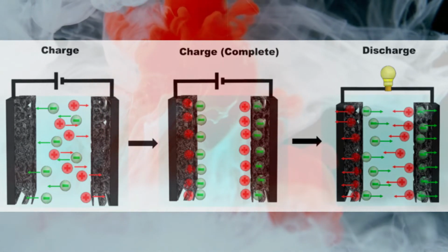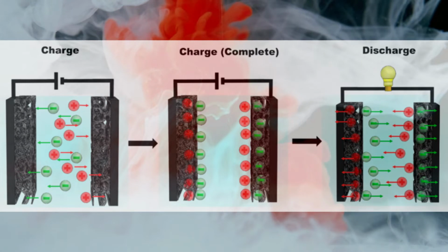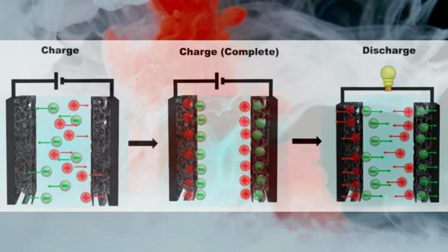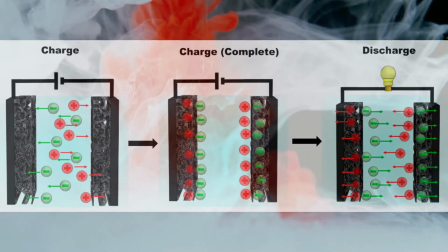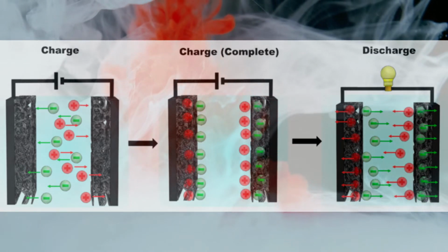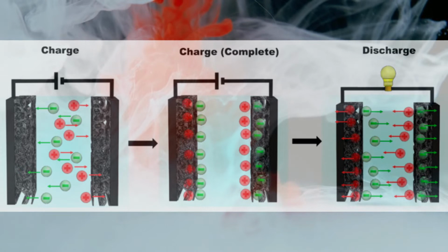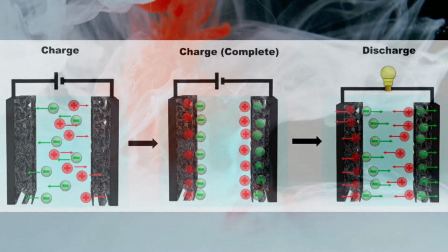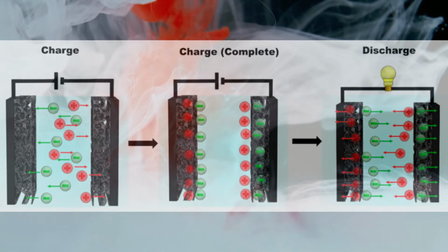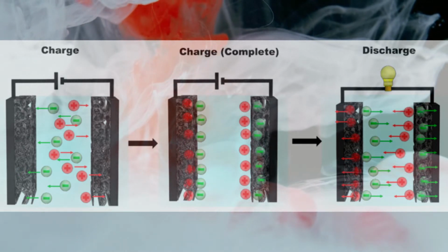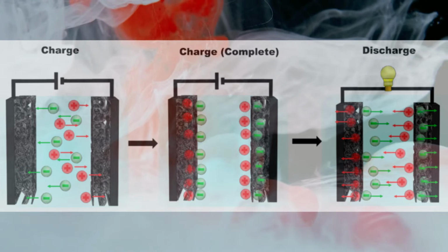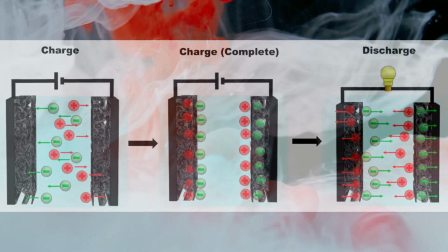Since the layer is composed of multiple ions moving, there is no major chemical reaction involved, such as in conventional batteries. This yields a superior charge-discharge life cycle. Porous carbon is used on the electrode to increase its surface area. The greater the surface area, the greater the charge that can be stored. Therefore, the supercapacitor with highly porous carbon nanomaterials is able to reach a higher capacitance.